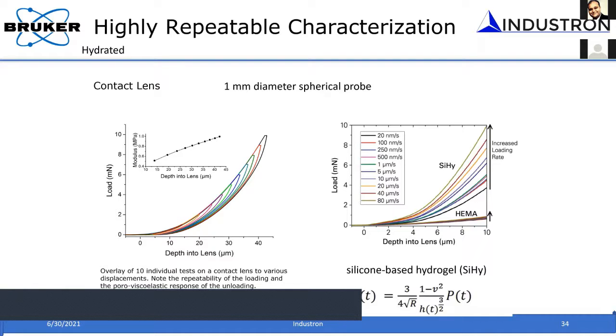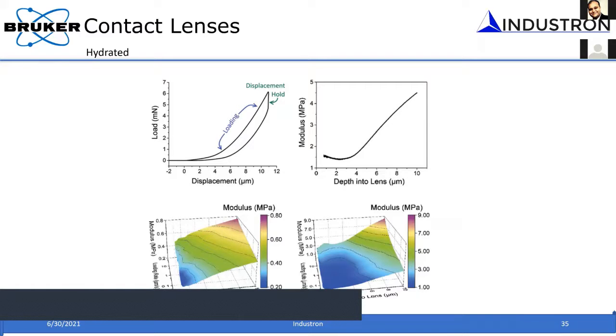There are two samples that I have shown. One is HEMA, which is acrylate based, and the other is a silicone-based contact lens. You can see the silicone-based contact lens here has a loading rate dependence, whereas the HEMA, which is an acrylate based contact lens, doesn't have a loading rate dependence. What I mean to show here is that you can do this even on materials like a contact lens, which is basically a hydrogel, and reliably measure the modulus of the material at any loading rate and make a good measurement.